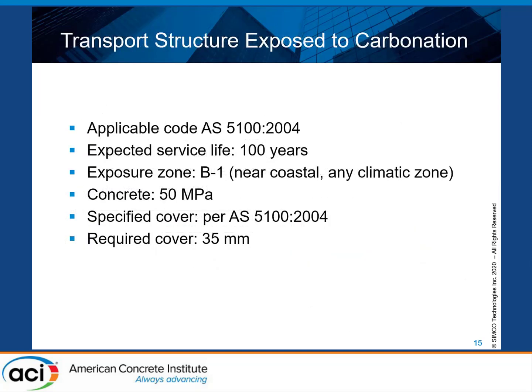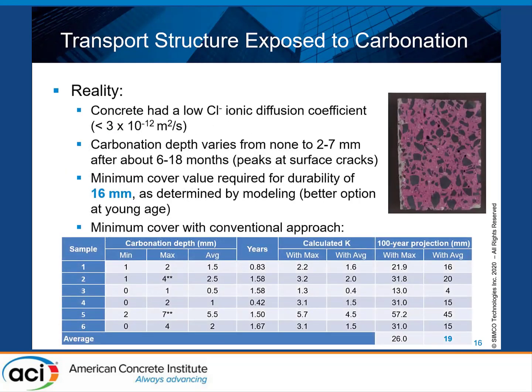The other example here is in Australia. I'm going to go fast. It was for carbonation. The required cover was 35 millimeters. I'm going to skip through that, but in reality, based on the concrete properties we were measuring that were much better than expected, we needed only 16 millimeters determined by modeling. And if we were using the conventional approach based on the measured carbonation at a given age, we were getting on average 19 millimeters. So modeling and the traditional approach gave much lower covers than what the code was requiring.